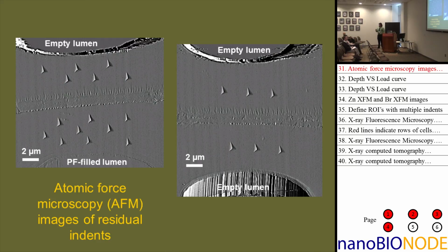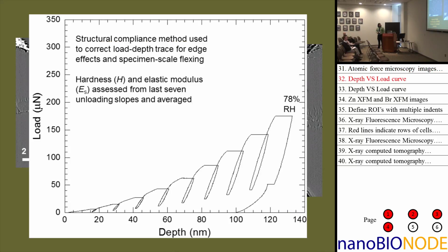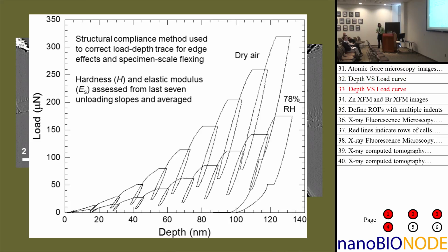We purposely use latewood because it has these nice thick cell walls that we can easily place the indents into. And here's an example of a multiple load indenting function, and we controlled the load such that the depths were basically the same between the dry and moist environments. Just from these indents, you can tell that there's a lot of moisture-induced softening that happens as you change the humidity in wood.